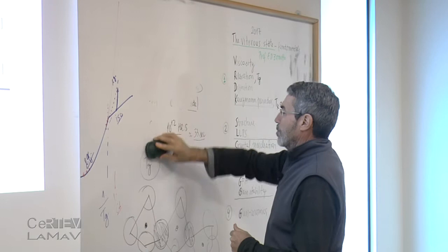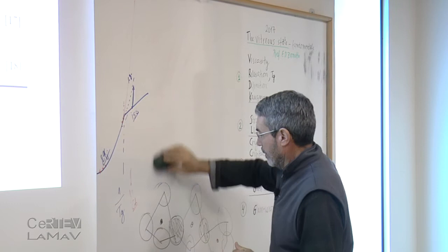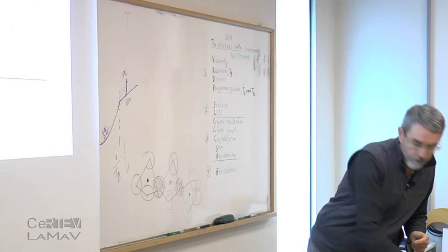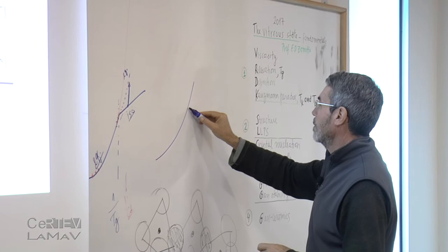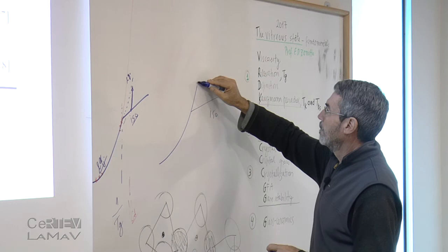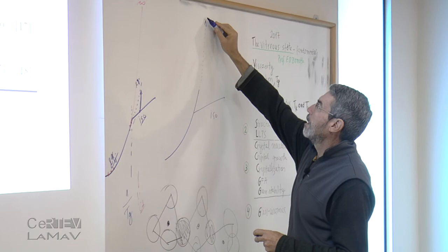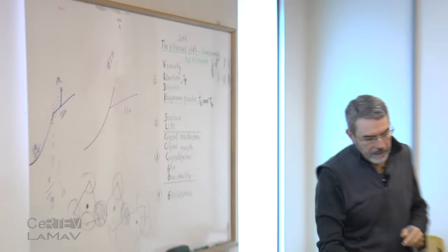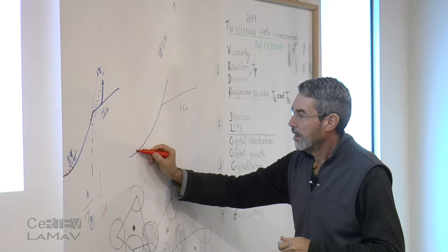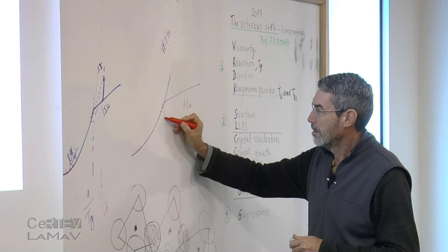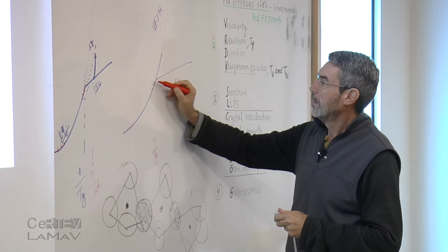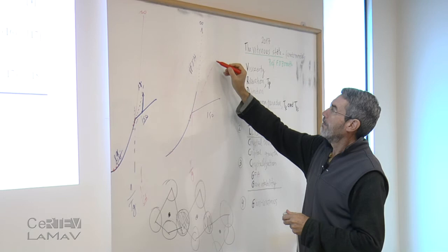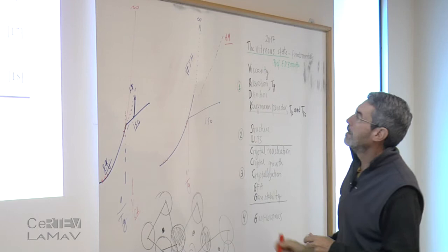So here's the overall picture. Equilibrium viscosity, isostructural viscosity. The Vogel-Fulcher-Tamman-Hess diverges at some temperature. The Avramov-Milchev equation goes more smoothly and never diverges, plotted against 1 over Tg, with these being data. But here, they work more or less equally well.